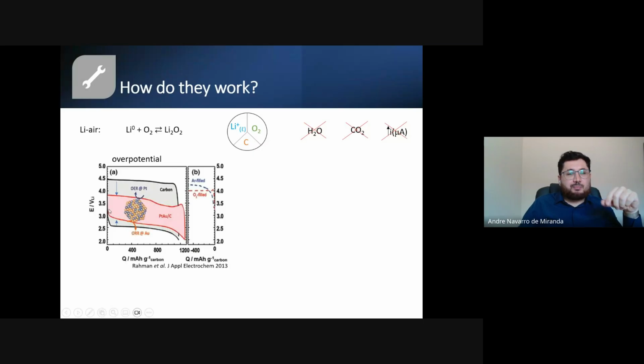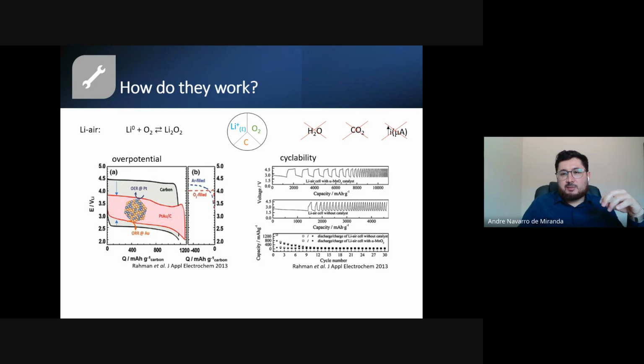Here we can see a big overpotential for the charge process. The equilibrium voltage here is about 3 volts, and for charge you use 4.5 volts. So it's a lot of distance between the equilibrium potential and the charge potential. In this process, we use catalysts to decrease this overpotential. The first catalysts studied in the literature were gold and platinum, but they are very expensive. After that, we have manganese as a catalyst as well. Manganese is a transition metal oxide. It's a little bit cheaper than platinum and gold, and works as well as the gold.